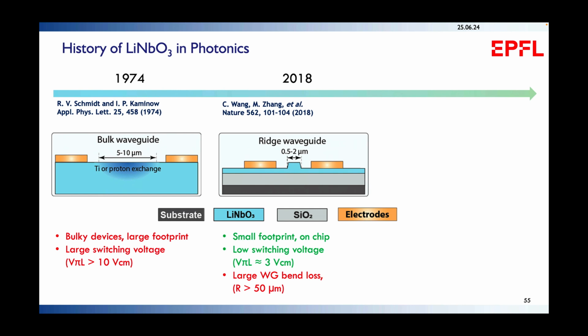Now the challenge of the material, however, is that it's very hard to etch. And as you see also in this image, typically you don't have fully etched strip waveguides, but you have these slight protrusions. And these protrusions are really a direct manifestation of the inertness of the material and the difficulty of etching the material with conventional etch chemistries.